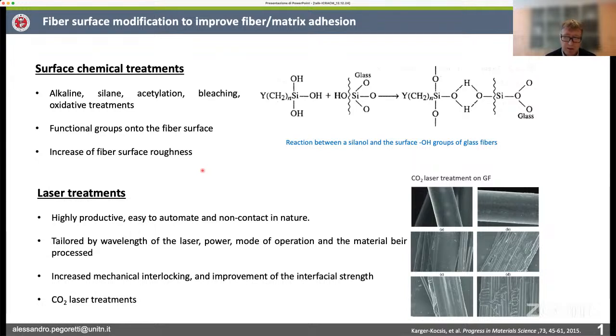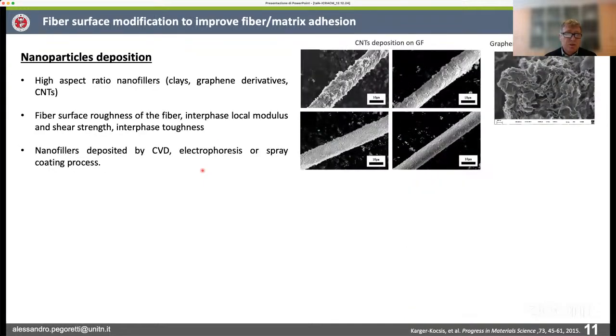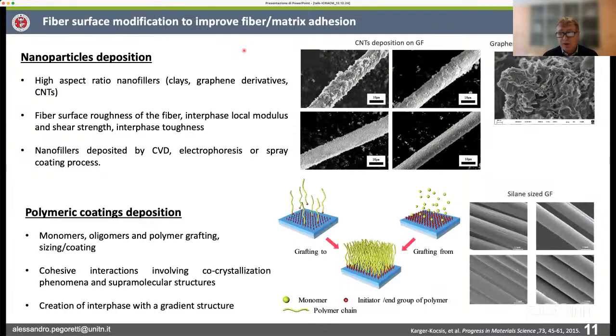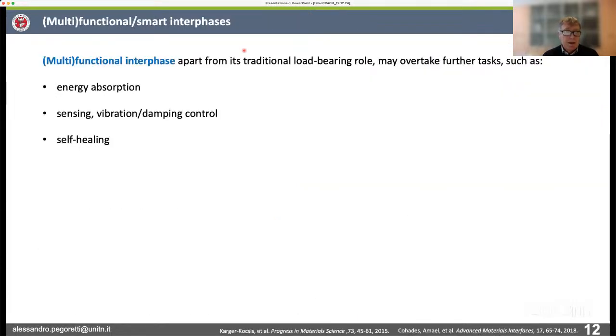These have recently been introduced due to the rapidity of these treatments and the possibility to tune the effect, as I will show you later. Another possibility is to deposit particles, for example nanoparticles, on the surface of the fibers, and I will also provide some examples in this field, or to deposit a continuous coating, for example a polymeric coating, on the surface of the fiber in order to tune some of the interfacial properties. Also in this case, I have some examples I can provide. This is why I call this talk multifunctional.